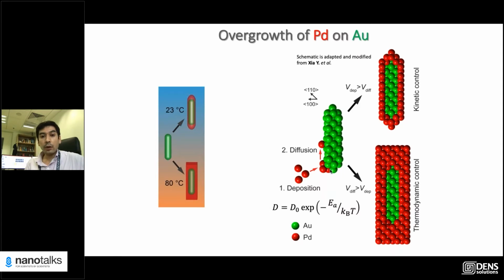So at a low temperature, most of your palladium atoms deposit predominantly on the tip. But since at a low temperature the diffusivity of atoms is low, they end up staying at the tip, and then your tip grows. But if you increase the temperature of the reaction, you are now cranking up the diffusivity of these atoms, and the surfactant molecules that are attached to the surface are also in a kinetic equilibrium, so they can detach and attach, which allows the atoms depositing at the tip of the nanorod to diffuse to form a cuboidal shape. Atoms can also deposit directly from the solution. And since you have a lot of surfactant in the solution, it predominantly dictates that the nanoparticle is going to grow into a cuboidal shape, with the lowest facet energies exposed to the solution.